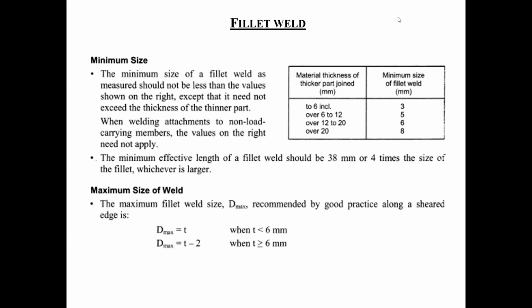Now, keep in mind what they're saying here. If the leg of my angle happens to be 9.5 millimeters, and the gusset plate happens to be 6 millimeters, you always go with the smallest thickness to determine what size of weld you should be using. That's why they say, except that it need not exceed the thickness of the thinner part. So, for example, if I have a 9 millimeter weld, I have 6 millimeters here.